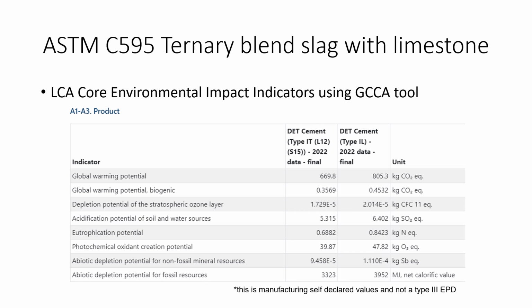Okay, when we look at it from a global warming aspect, right? Taking that same cement, the only difference we made was we now added in the 15% slag without it being on the dryer, right? We went from 805 to 669, right? So you can see we're moving that needle down again when it comes to the global warming aspect. Now this result actually came out of the GCCA tool.